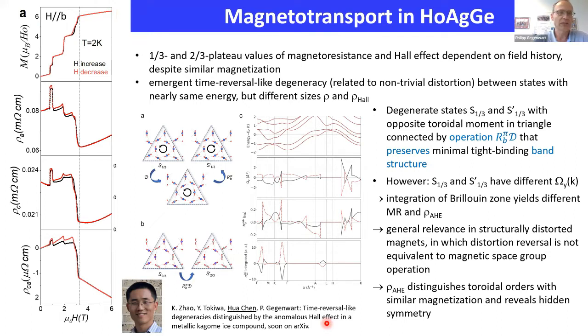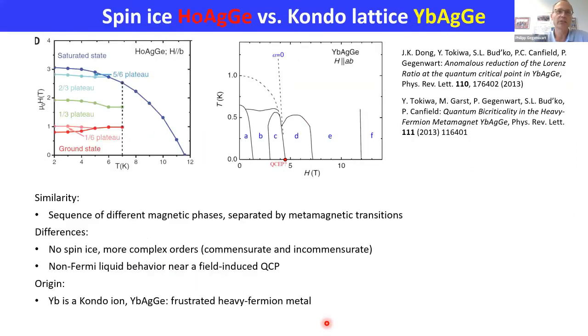All right, so up to now there was negligible Kondo interaction. Of course, we can ask what happens if we replace holmium with 10 f electrons by ytterbium, which has 13 f electrons, so it's a Kramers ion, and which has just one f hole, and you know this one f hole can get unstable, and there are a lot of spin fluctuations going on, and the Kondo effect can lead to drastic changes of electronic structure.